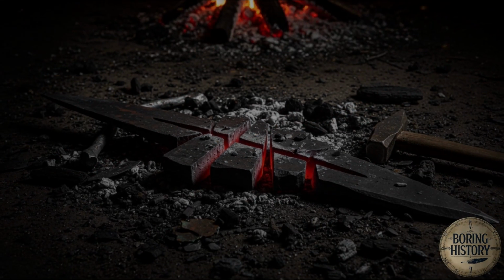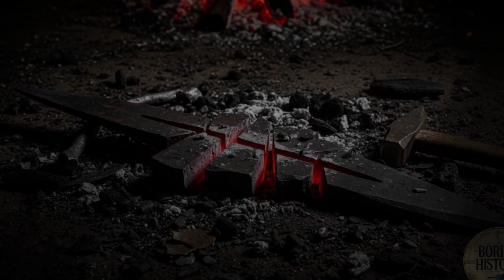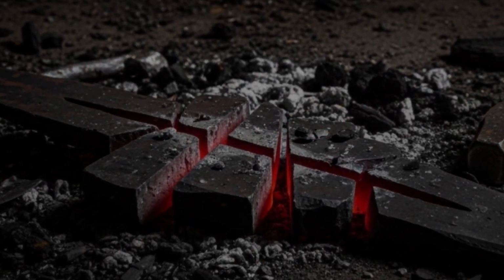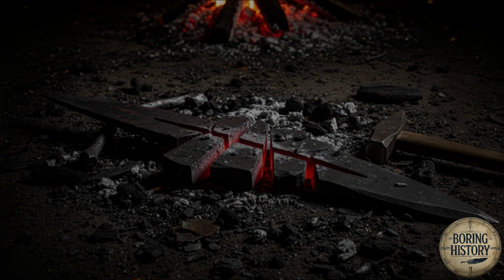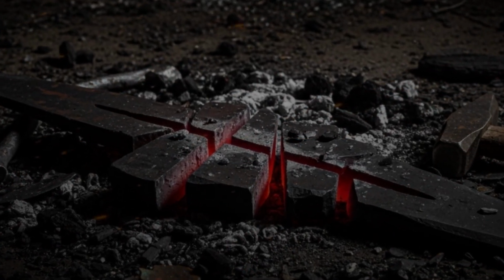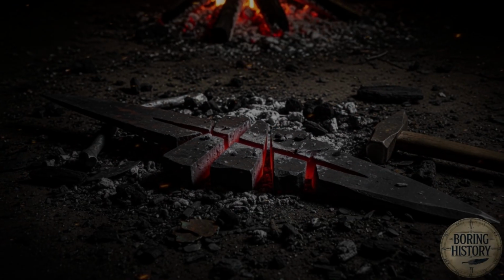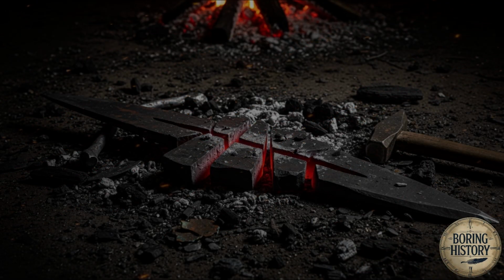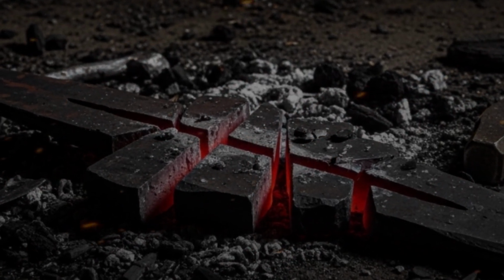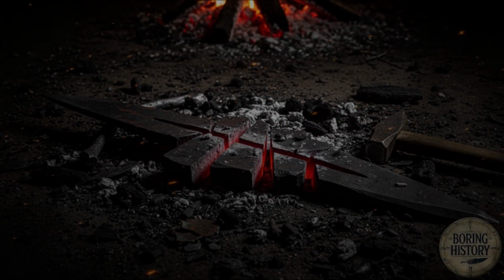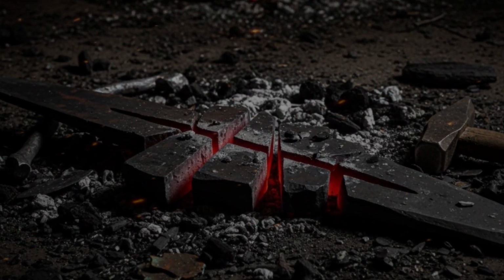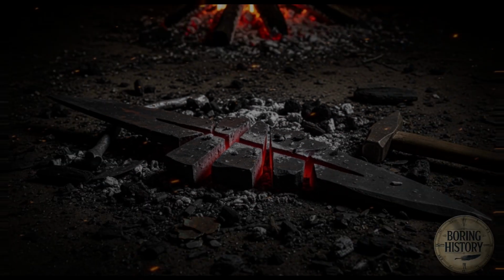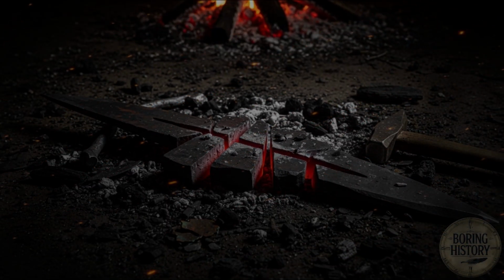The crucible steel in the Ulfberht had no slag inclusions to contract against themselves. The carbon was distributed evenly through the metal, not concentrated at the surface. The grain was fine and clean, and gave the cold no foothold for its particular destructiveness. The blade remained exactly what it had always been, because it had been made to be exactly what it was, in all conditions, without compromise.